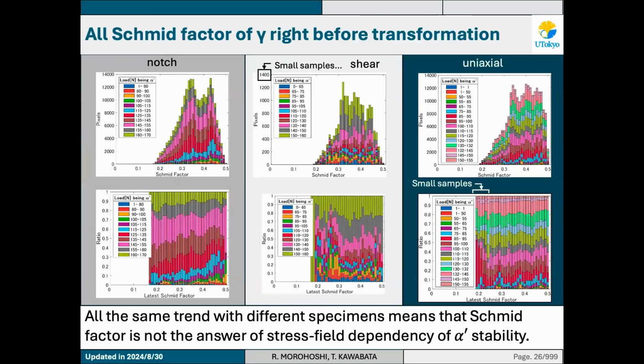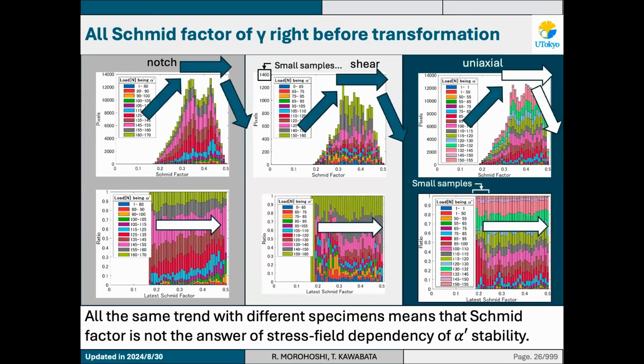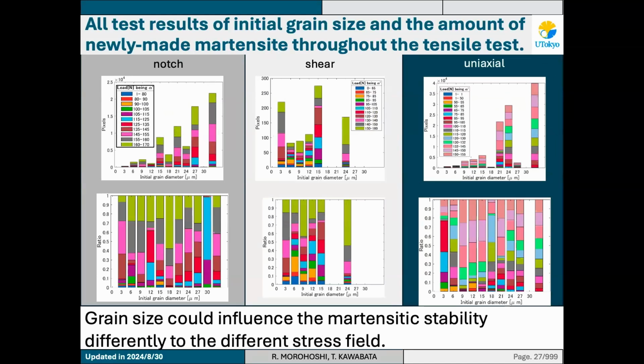And this is all the results with different triaxialities. However, they indicate all the same trends, which means that the Schmid factor is not the answer to the stress field dependency of the martensitic stability. So next is about the grain size.